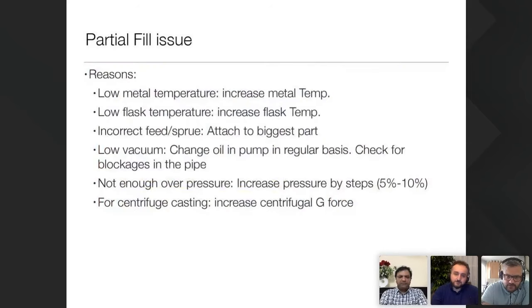And also the correct investment powder. Yes. With the correct investment powder, it will have the correct permeability to allow the alloy to flow in the flask. There is an example which we will speak about later on, but manufacturers should understand that the investment powder that is cooked in the burnout is like a sponge, right? It has some permeability, not as much as a sponge. It's a stone with some permeability. So if the permeability is good in that investment, when you have this pressure difference, the vacuum effect will be more efficient than if you have a stone that doesn't have any permeability, right? That's what you mentioned, Dave? Yeah, for sure.